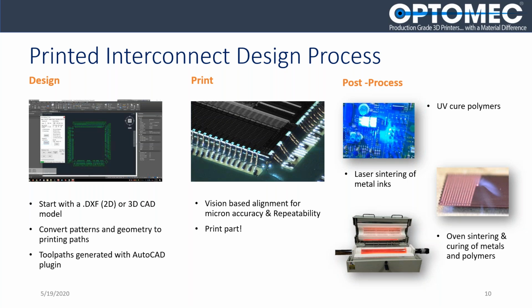All of the inks that we print, whether they are polymers or conductors, are green, meaning that the particles are not sintered. We have to add energy into them in order to make them functional. So many of the fillet materials, these materials that you see that the interconnect is actually riding on, are made with UV curable materials. And then we use different either photonic or laser-based sintering methods or oven sintering methods to cure the wires and make them electrically conductive on the substrate.